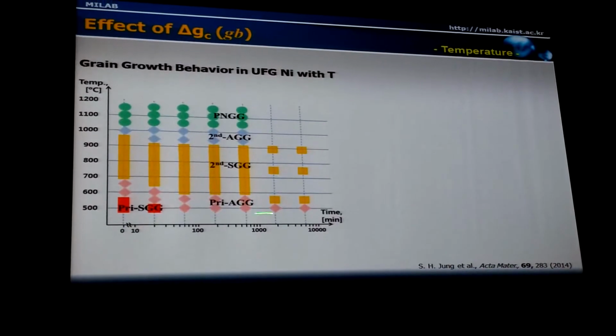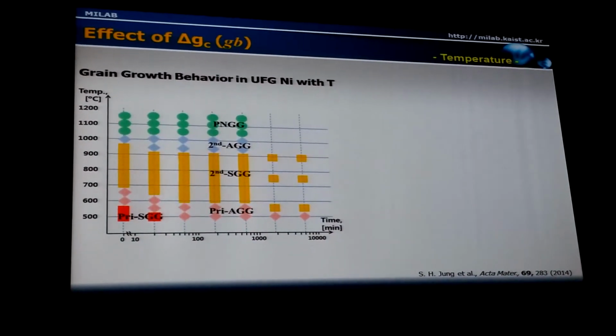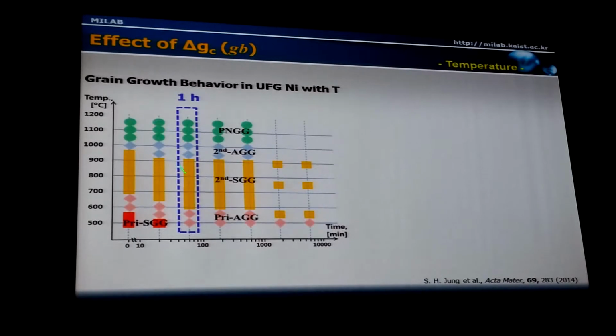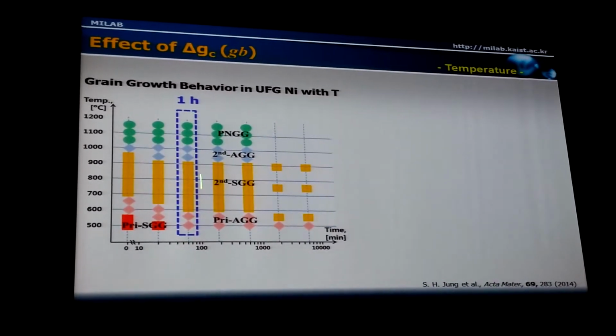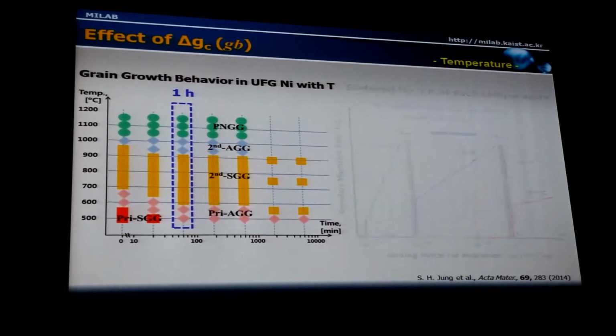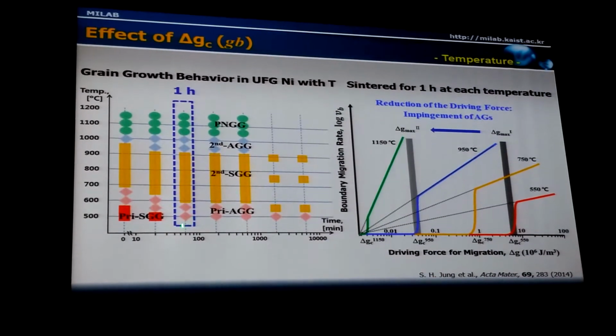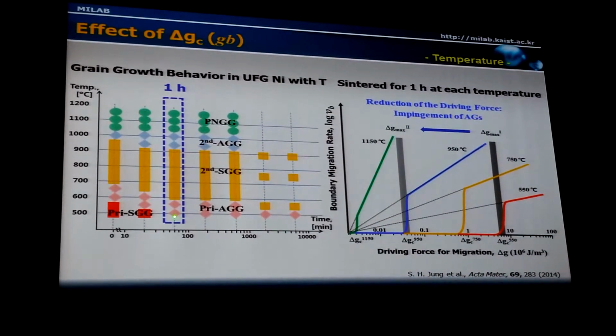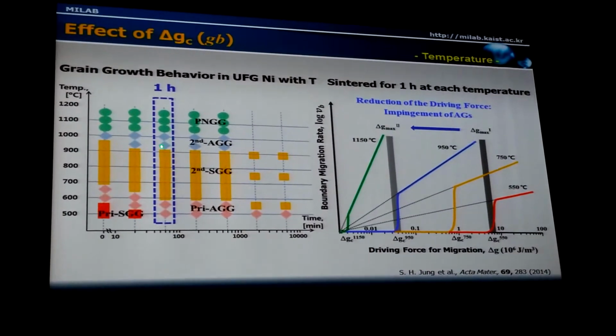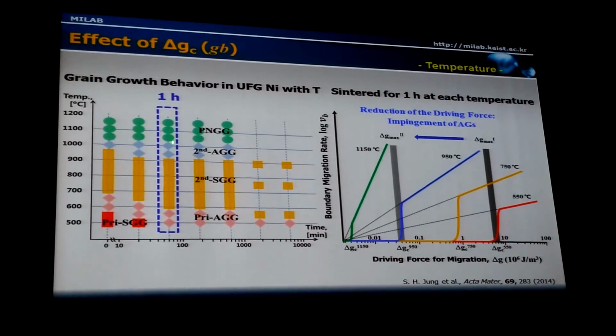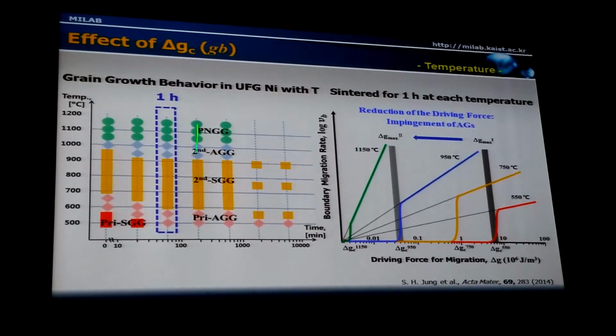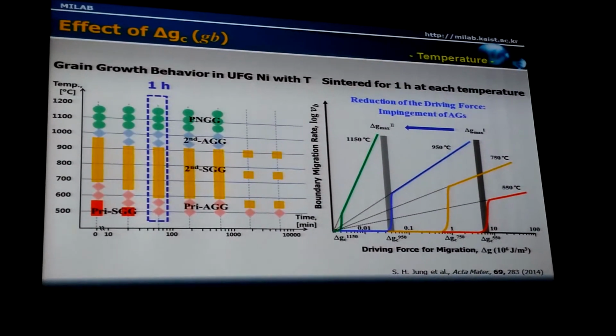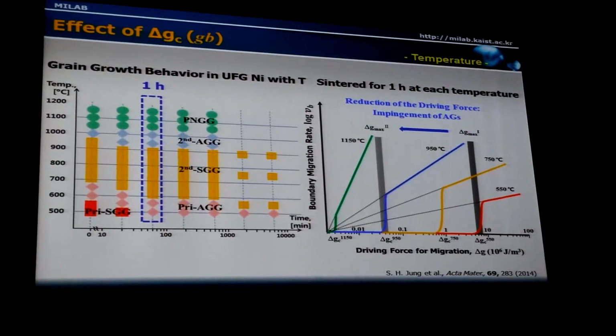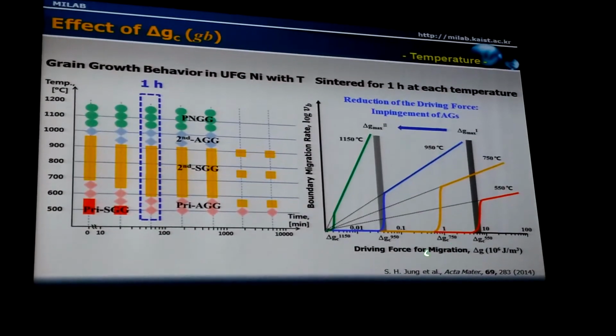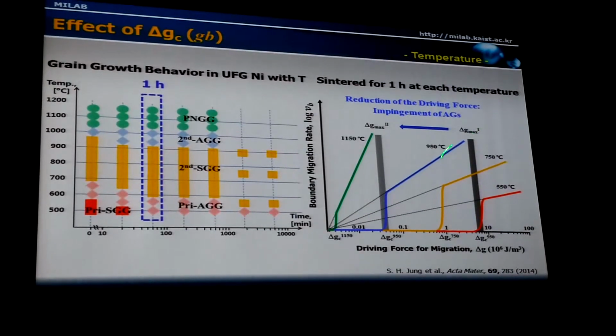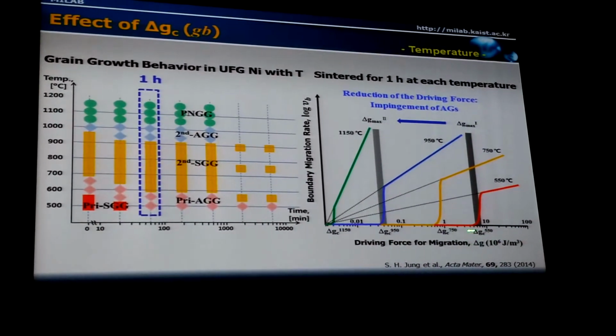And we prepared many samples under different experimental conditions. Take, for example, the samples sintered for 1 hour. At low temperature, primary abnormal grain growth occurred, then stagnant grain growth, then secondary abnormal grain growth, as I explained just before, and then normal grain growth. These variations of grain growth behavior in the same sample, depending on temperature, can of course be well explained by the variation of the maximum driving force and the critical driving force with temperature.